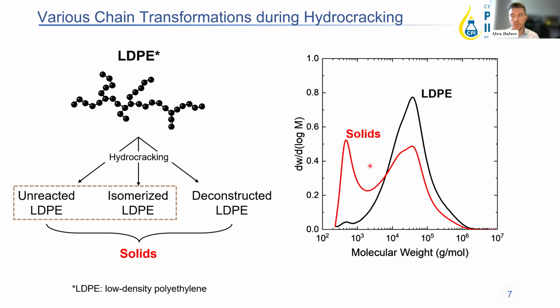And what you can see is the solids curve is a wider distribution, with a bimodal-like feature. But the high molecular weight tail of this solids curve looks nearly identical to the high molecular weight tail of our neat LDPE feedstock. And so we can take our LDPE feedstock distribution and fit that inside of the solids curve to help us define this intact LDPE fraction. And that is going to contain all of the unreacted and isomerized chains.